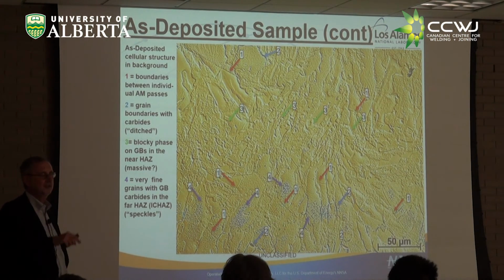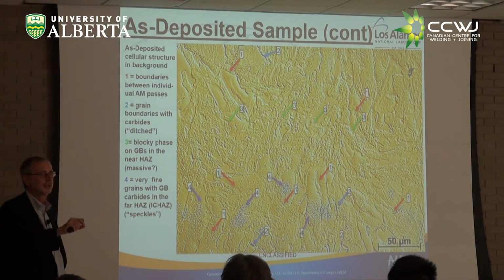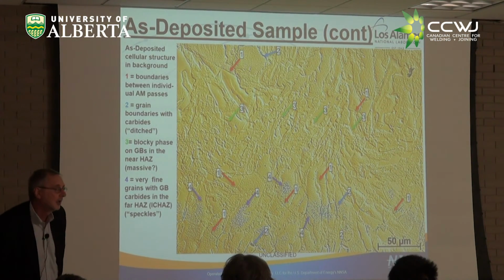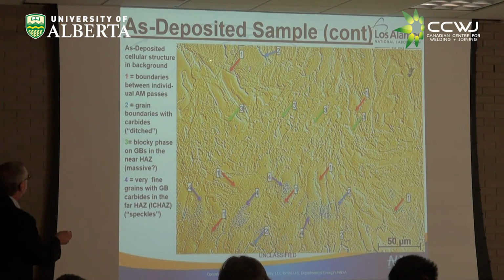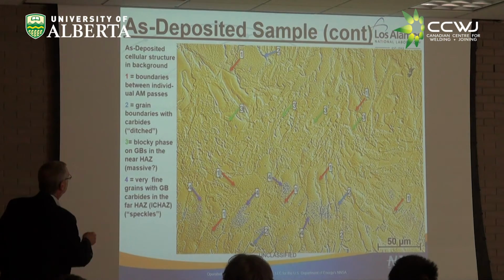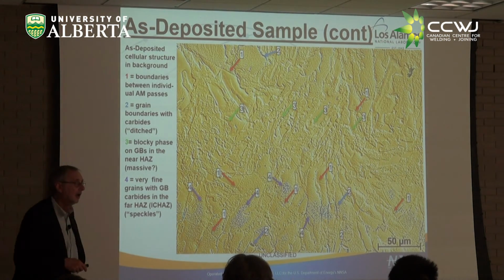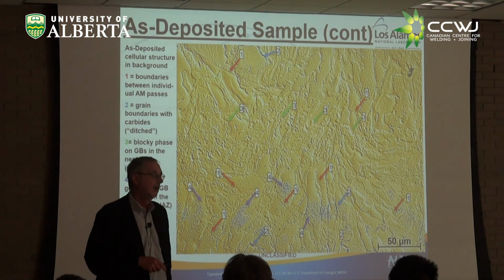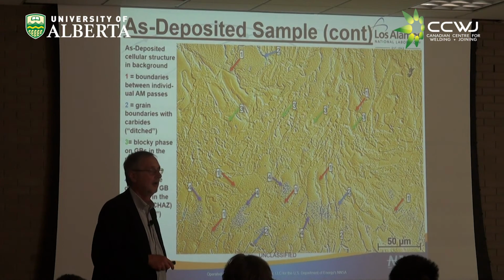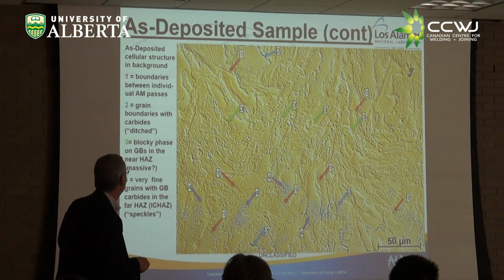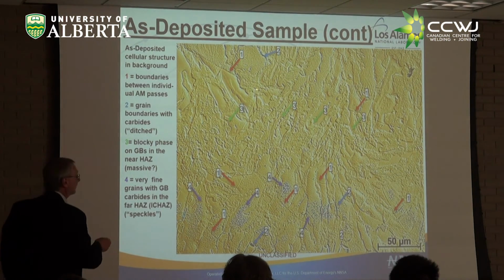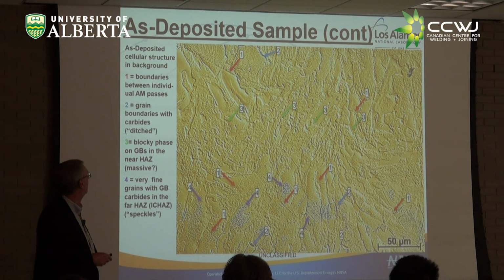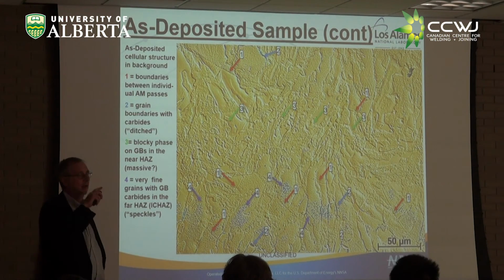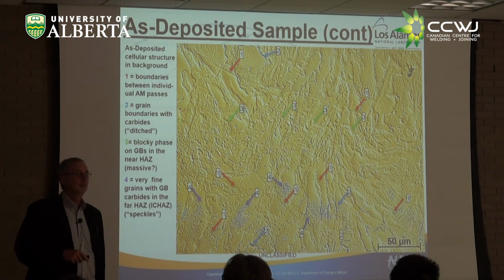Usually when you see retained austenite, you see little islands or slivers. Composition at the boundary, like the smooth phase and the other phase. At the face right here? Yeah, there's some composition variation. Where delta ferrite is there, chromium and manganese are also going to increase in composition at that phase, at this interface. Yeah. And hardness is also very different.